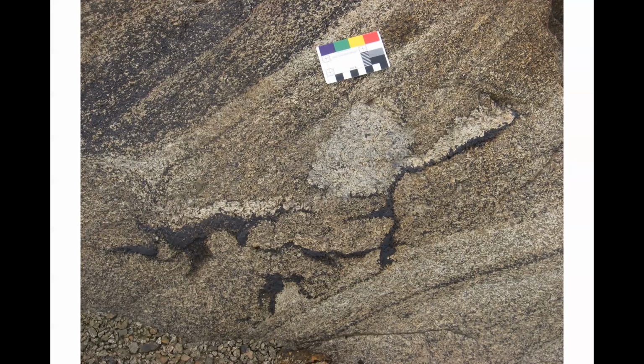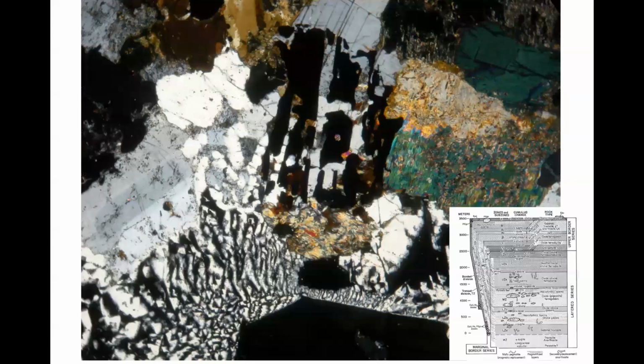This is a photograph from lower zone C, where we've got a little pocket of late stage liquid, and it's unmixed. And the dense iron-rich liquid has gone down here with a bit of disruption of the underlying mush. And then this is the silica-rich conjugate that's floated to the top and crystallized as an anorthosite. Well, not really an anorthosite, but very, very plag-rich. So we've got these two immiscible liquids in this mushy layer.